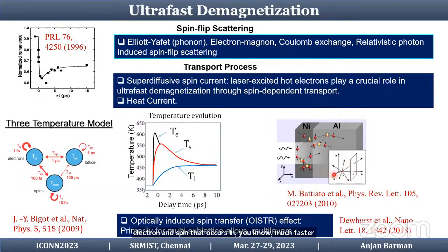And this is the superdiffusive spin transport, which shows that the electrons become mobile because they are shifted from the D band to the SP band, where the mobility is faster, and they travel at two different velocities for the up spin and down spin, and that causes this ultrafast demagnetization through the spin transport process. That was proposed in this paper in 2010.